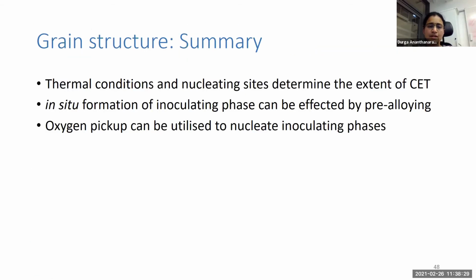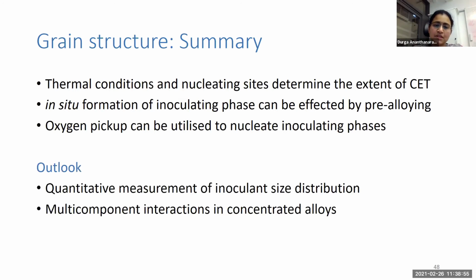So summarizing this part, the thermal conditions and the nucleating sites, their size, density, and so on determine the extent of CET. In situ formation of the inoculating phase is possible by pre-alloying the powder, as we showed here. And we also saw that the oxygen pickup in the system can be utilized to nucleate inoculating phases. From a modeling perspective, if we want to do really quantitative predictions of CET, it would be great to have more measurements of inoculant size distribution, and also to look at the effect of multi-component interactions in concentrated alloys, and not just use dilute solution approximations.